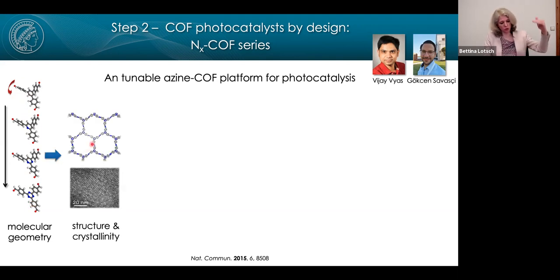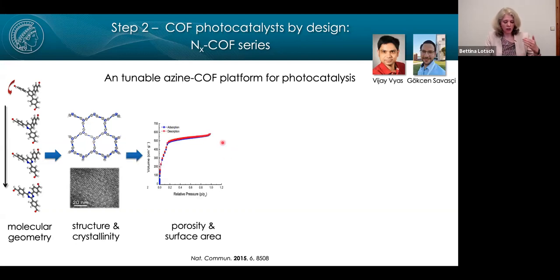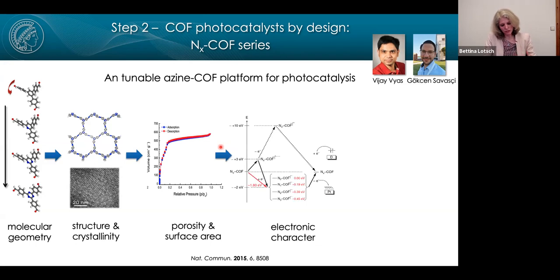So we're seeing, as we go from top to bottom, a planarization of the system. We see an increase in crystallinity and structural definition. Also, we see an increase in porosity on going from the top to the bottom. And we see a difference in electronic character as well. So as we introduce nitrogen, the system gets more electron poor and therefore is able to stabilize the radical anion that we believe is formed as an intermediate during photocatalysis. And we have also evidence that this indeed happens.